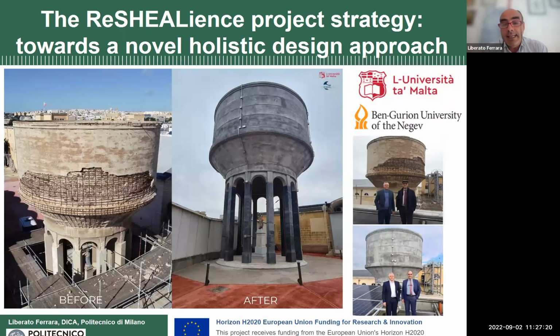And this is the example of the last pilot. This is in Malta. It's a water tower in the area of the Grand Harbor in Valletta in Malta. You can see how it was 5 years ago when we decided to have it as one of the pilots of our project. It was severely degraded by airborne chlorides, but also by the action of wind suction in this case, which together with the sand particles and the chloride particles brought by the wind, created also this strong erosion on one side of the structure.